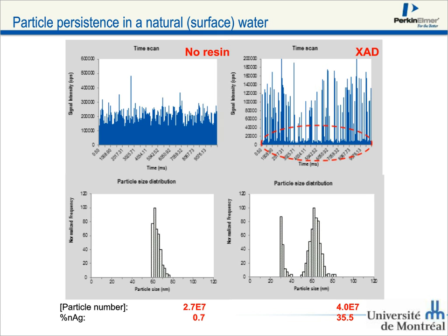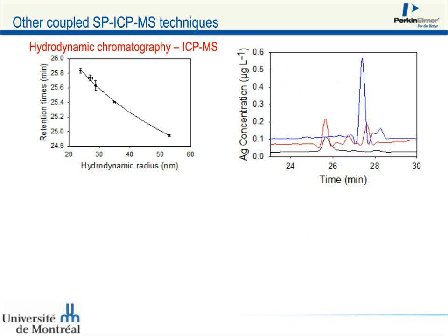So finally, I just want to show you a couple of applications with hydrodynamic chromatography. Again, I showed you that the retention times are a function of our hydrodynamic radii. You can just pump that directly into an ICP-MS, and the ICP-MS, with its very low detection limits, will give us really nice information on the particle concentrations, and by knowing the retention times, we can get the particle sizes. In this case, the red, black, and blue curves were done with 3 different matrices, but with exactly the same peak. So you see that the retention times are affected not only by the nanoparticles themselves, but also by the matrix.